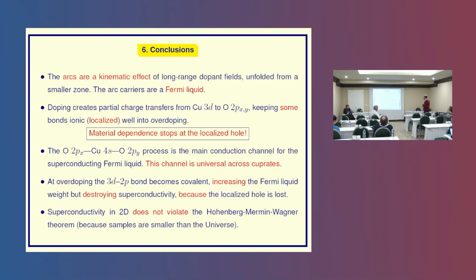Second, these partial charge transfers, which are created by doping, induce a sharing of this localized hole between the copper and the oxygen, and this sharing is the last of the material dependence. Beyond that, when you are already on the oxygen, the cuprates are universal, because the chemistry involved in the oxygen metal, which is so created, is determined by very few overlaps, which are the same in all cuprates, because the lattice constant is the same in all cuprates, okay?